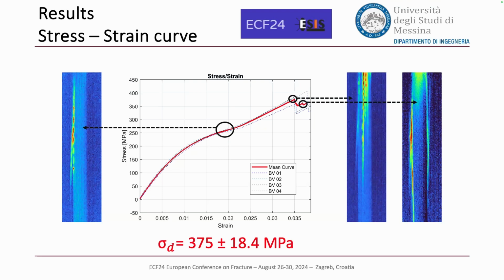Here there is the stress strain curve. The curve is not increasing until the failure, but we can notice that there is a first load loss that is due to a fracture in the external part of the specimen. Then we have a clear load drop that corresponds to the delamination of the specimen, followed by other fracture on the external part.